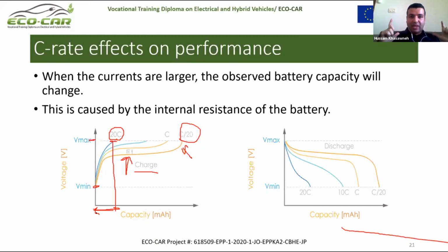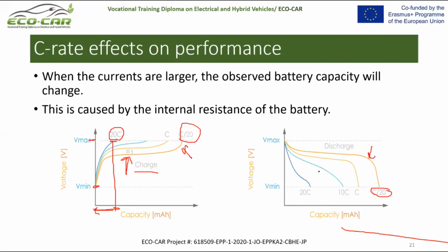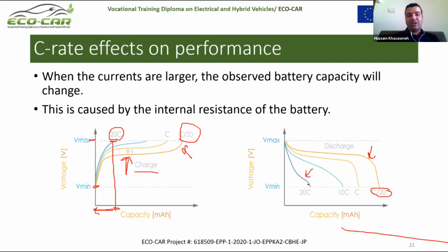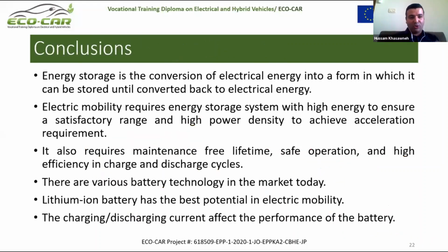To maximize the capacity, the actual observed capacity, it's better to charge and discharge the battery slowly. By doing this, you will extend the life. And my friend Florian will talk about this in a second. The opposite happens during discharge. If we discharge with a very low current, the curve looks like this. But if we do it very, very fast, we are just using a portion of the capacity. And that's far from ideal. There is much more to talk about, but I know the time limits, so let me conclude.